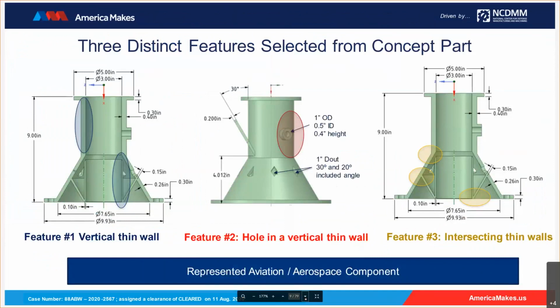Thank you. So once we had those singled out, you can see there are three distinct features which we could identify based on the HPC part itself. You have the vertical thin walls, which are of different thicknesses that are built using the DED process. We have the holes within the thin walls itself, which could be in a rhombus or teardrop shape, depending on the choice itself. And then the third feature is where we have the intersections of two different thin walls at a point, one usually meeting the other at an angle.